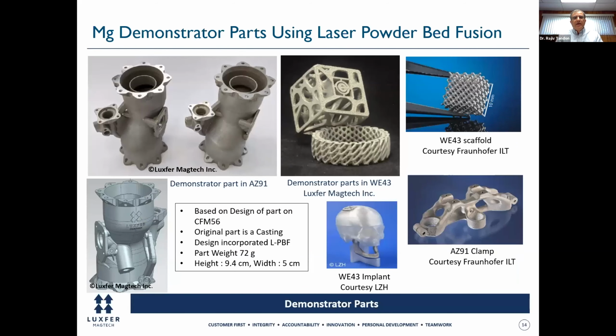So one of the things you see there is the smoke generation, which is very, very common for magnesium. And this is really the area that people most report, in terms of addressing the parameter optimization. That's really where most of the focus tends to be in terms of reporting: the laser power, the scan speed, and the hatch spacing, etc., to be able to achieve the high densities that you need.